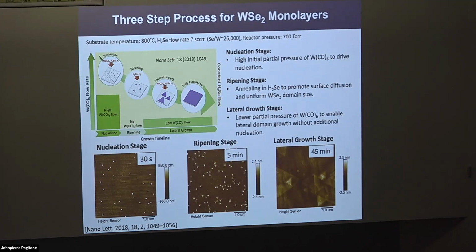This here? Yeah. So in the right one, why do we see step edges? Like not the trunk part? This step edges, this is the sapphire step edge. Yes. But you can't see it in the earlier AFMs? Yeah, so what happens is, you start off with a surface that looks like this, and over time you're annealing the sapphire, right? And so the sapphire also has steps that are forming, and you also have step bunching and meandering happening on the surface. So that's why that's happening.